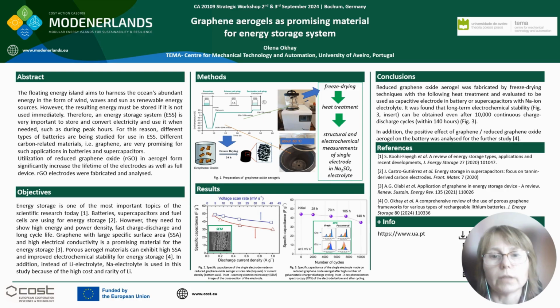So, an energy storage system is very important to store and convert electricity and use it when needed, such as during peak hours. For this reason, different types of batteries are studied. Graphene family materials are proposed as electrode materials in batteries and supercapacitors because of their high chemical stability and high electrical conductivity. In the presented work, graphene oxide in aerogel form was prepared by the freeze-drying technique. You can see it in figure 1. It was heat treated to get a highly porous and conductive material. Such materials were used for the preparation of composite electrodes.